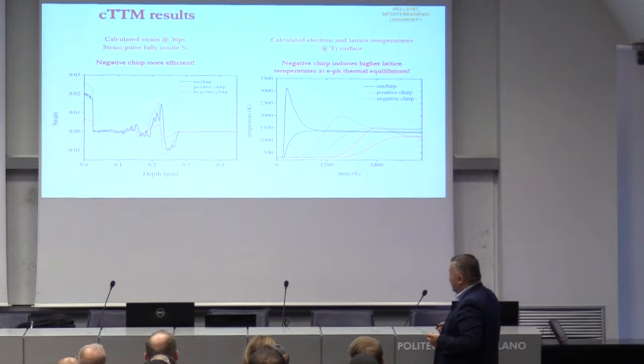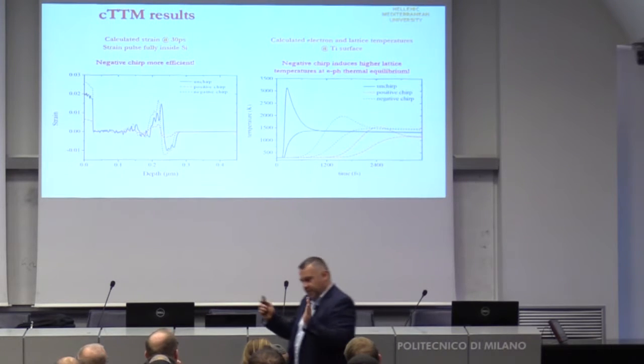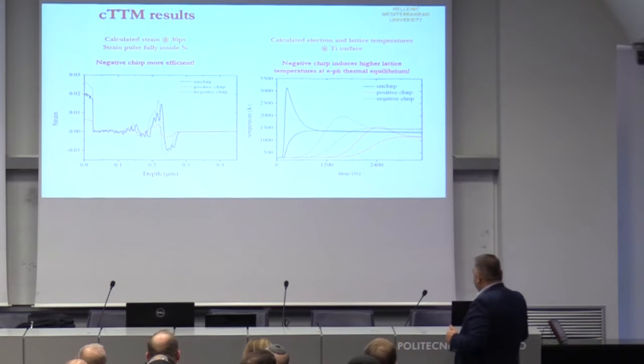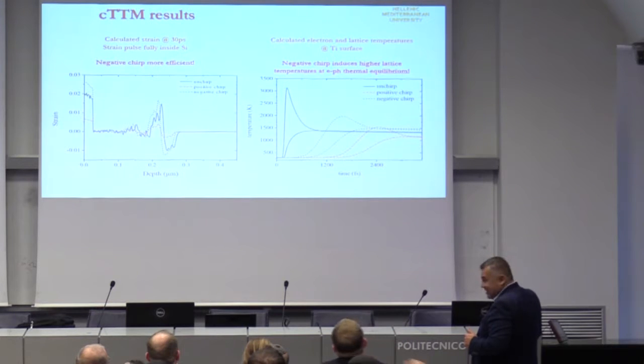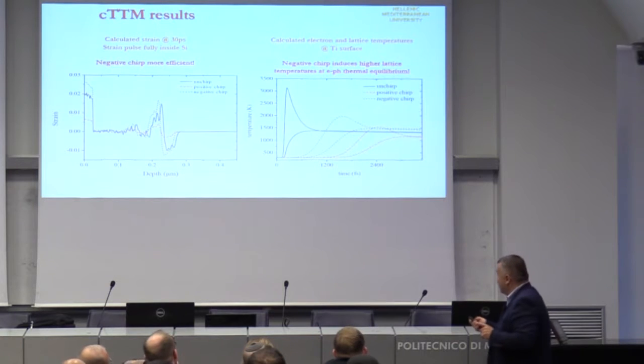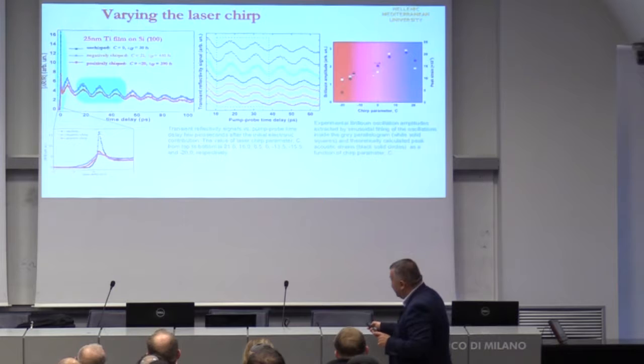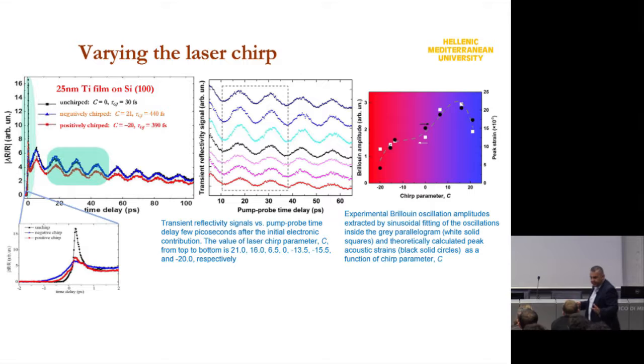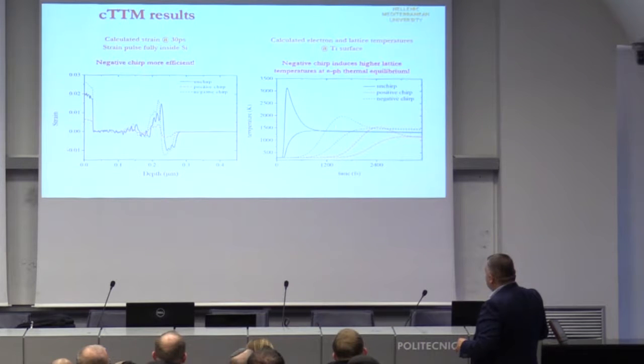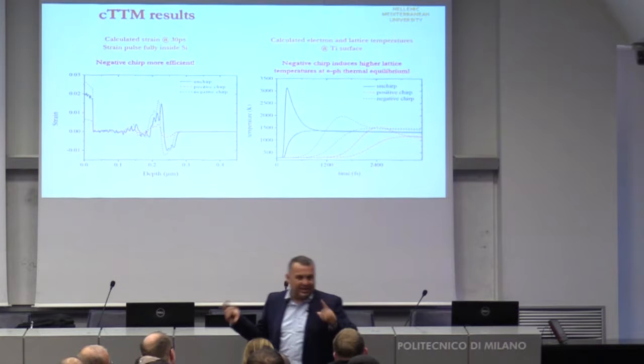You see here that the negative chirp produces higher strain than the unchirped pulse, and much higher than the positive chirp. I mean the same chirp magnitude, but negative and positive. And if you do the calculation, you see here that the maximum electron temperature is higher for the Fourier limited pulses, as we have seen in the experiment. Here, the maximum reflectivity change is for the Fourier limited pulses, while for negative and positive chirp, more or less we have the same behavior. But the thermalization energy between electrons and lattice is much higher with negative chirp. It is the interplay between electron-phonon lattice interaction and the photons.